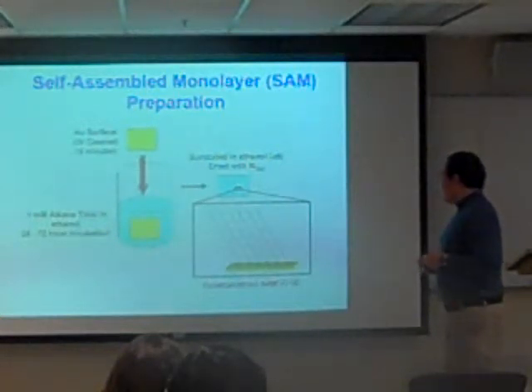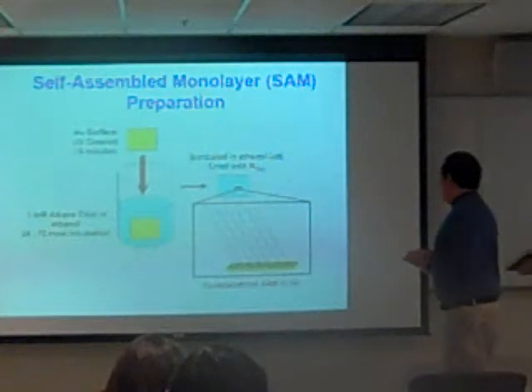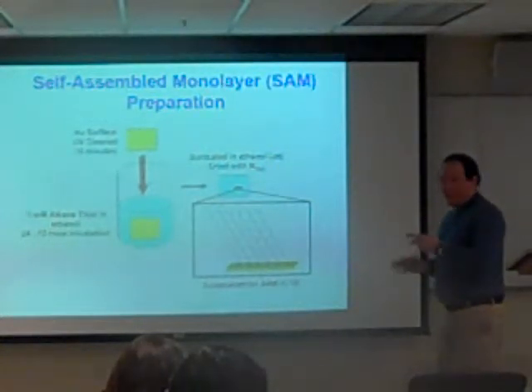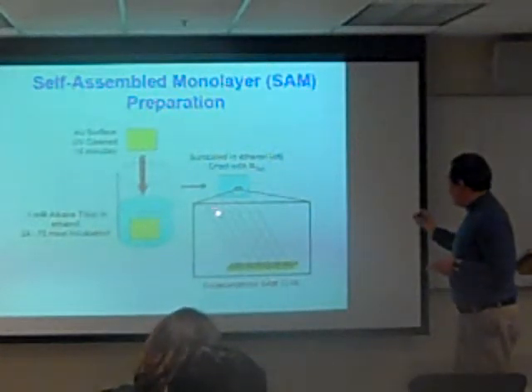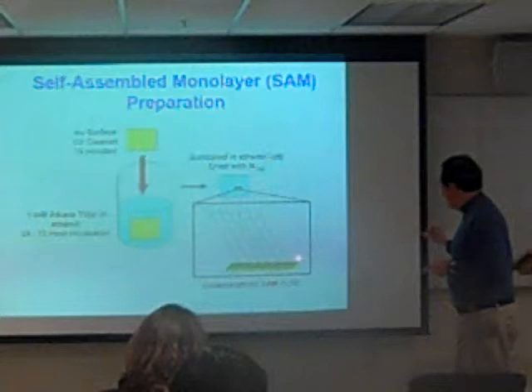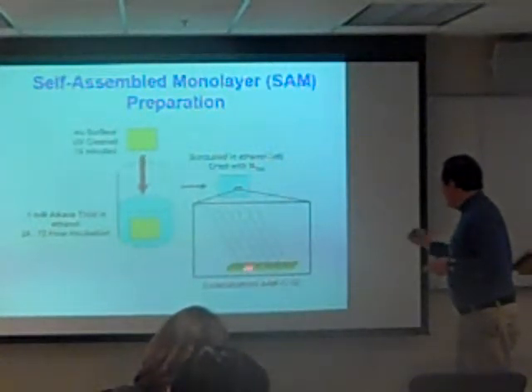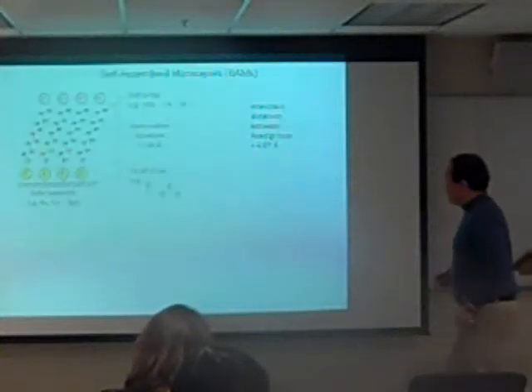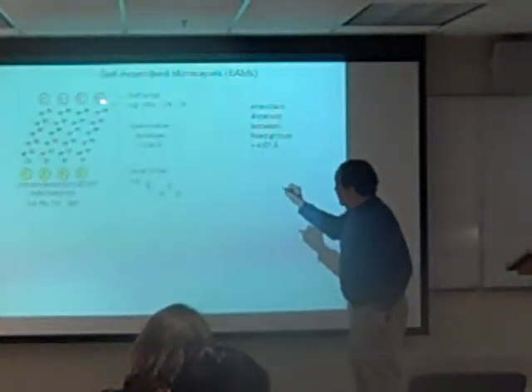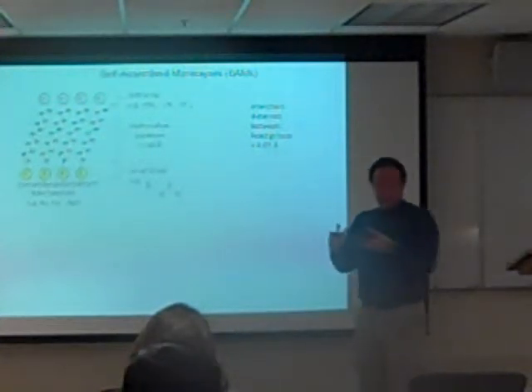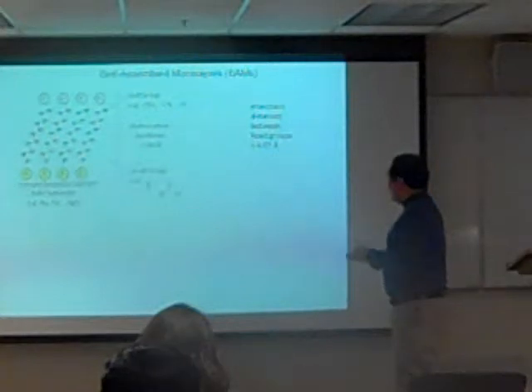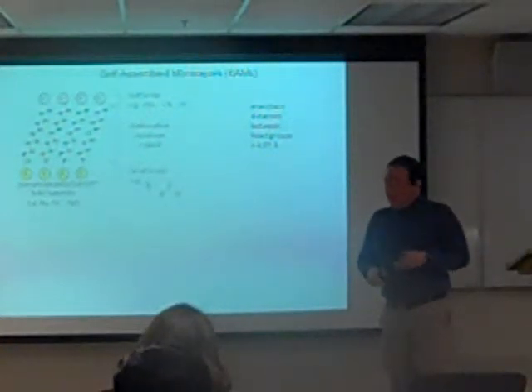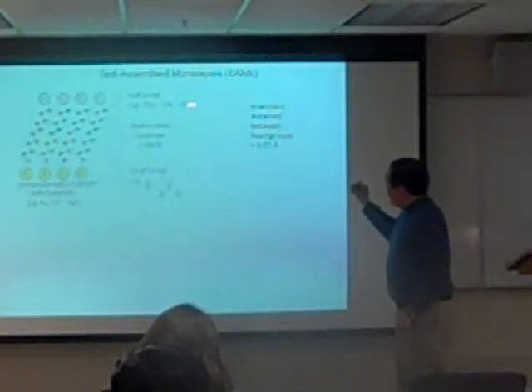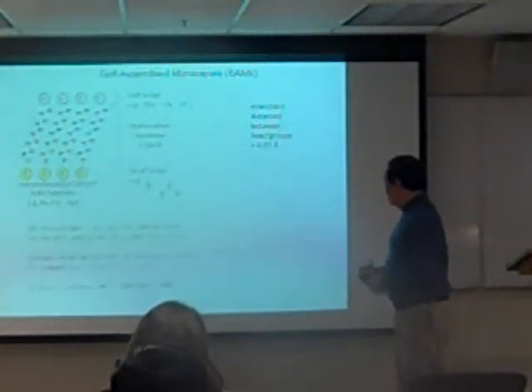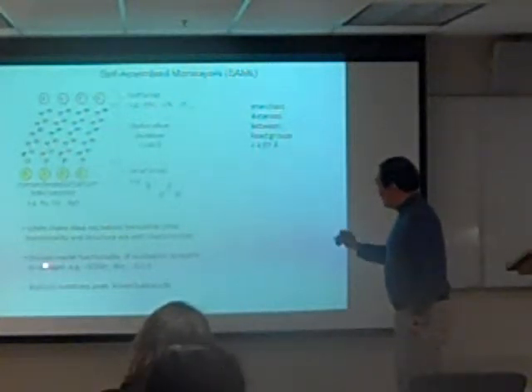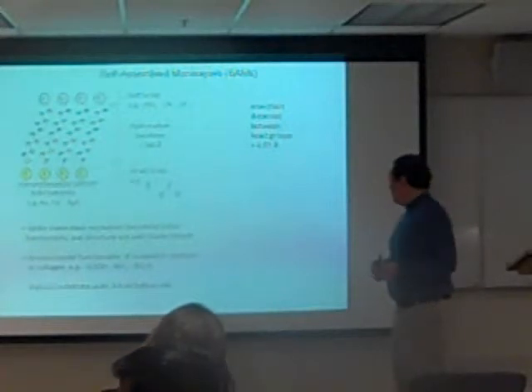And what was discovered by the group of David Allara and Ralph Nuzzo back at Penn State University in the 1980s or so was that if you did this, those molecules will self-assemble in an ordered manner, so that the sulfur attaches fairly well to the gold surface. And then the head groups, their positions are very well known. They're like 4.97 angstroms apart. We know it's very ordered, and we can put down end groups of our choice. So these make very nice surfaces for very well-defined cells.